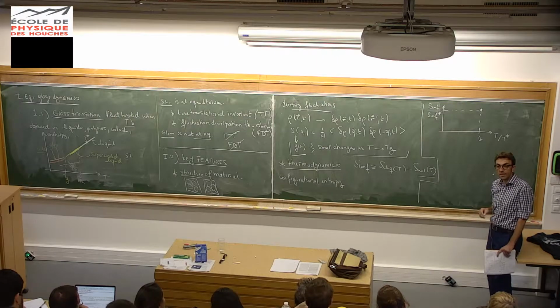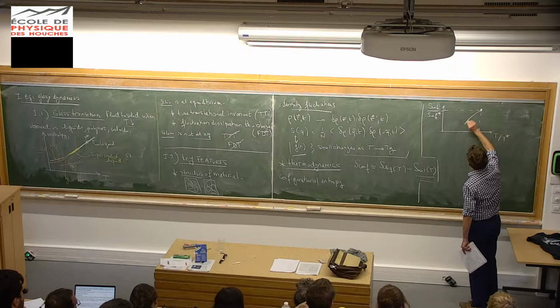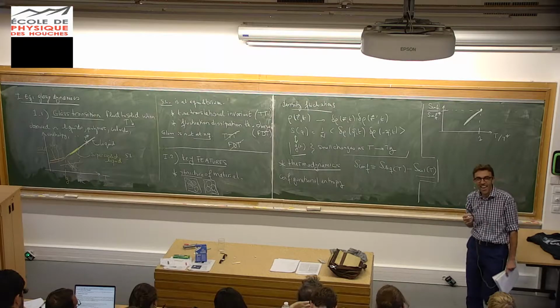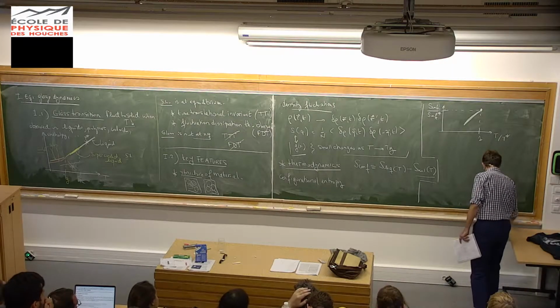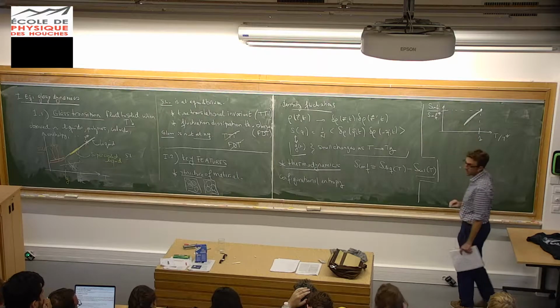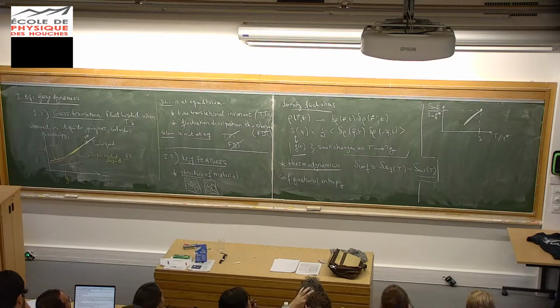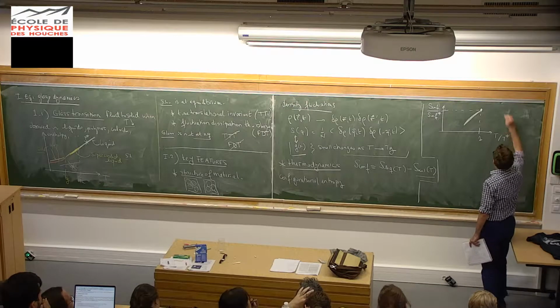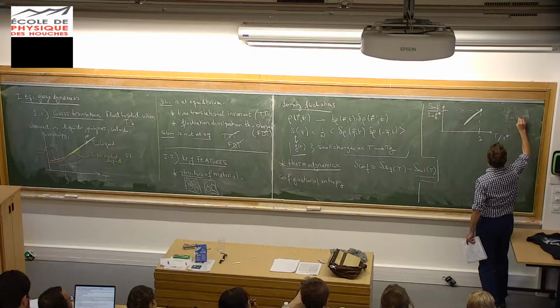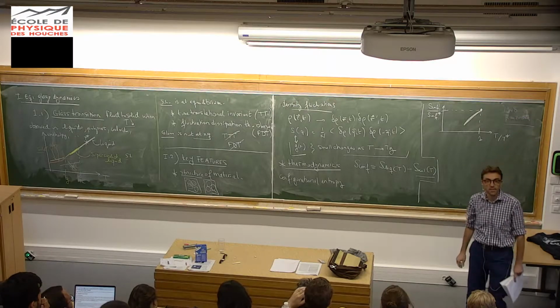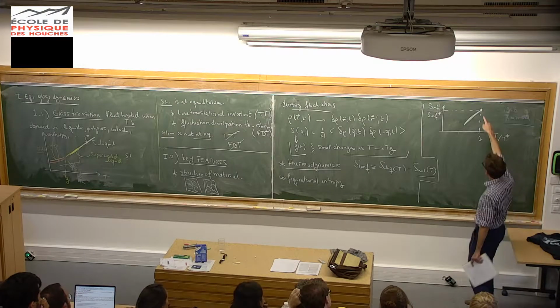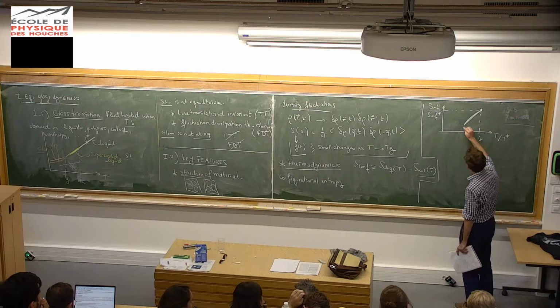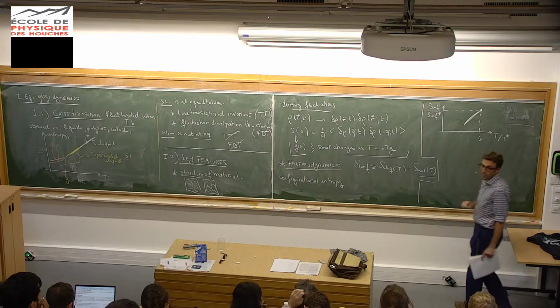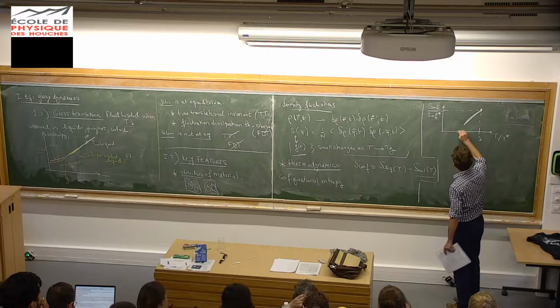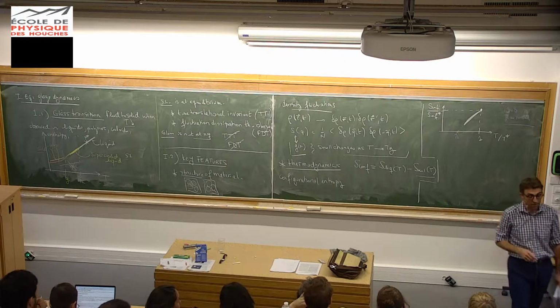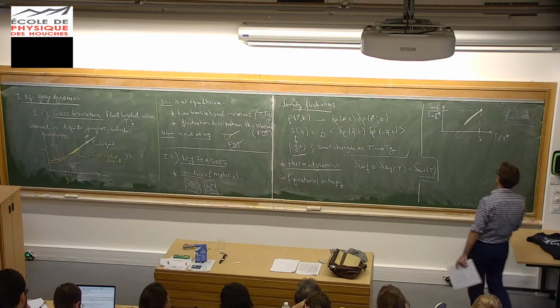So the question is how much the entropy decreases as you decrease the temperature, and experiments look like this. This is where you show how strongly you believe in thermodynamics. Of course in the experiment you reach Tg here, so the system falls out of equilibrium, and then you cannot measure the configurational entropy lower. That was shown in a paper in 1948 by Kauzmann, who compiled tens of experimental works on this, and he said, well, that's strange, because this configurational entropy is changing quite a bit as I approach the glass transition, to the point that if I extrapolate this to low temperature, there seems to be a temperature, now called the Kauzmann temperature, where this configurational entropy maybe would vanish if this behavior persists.